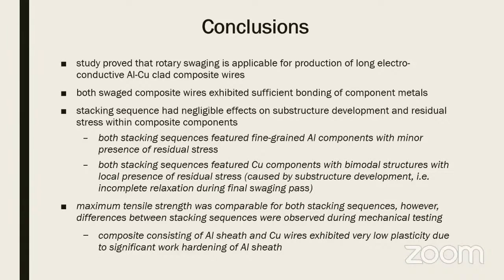We saw that both the stacking sequences featured fine-grained aluminum components with minor presence of residual stress, and we saw some residual stress in the wires of both the copper components in both the stacking sequences. That phenomenon was mostly caused by substructure development, so by the presence of bimodal structures, and this was primarily due to incomplete relaxation during the final swaging pass.